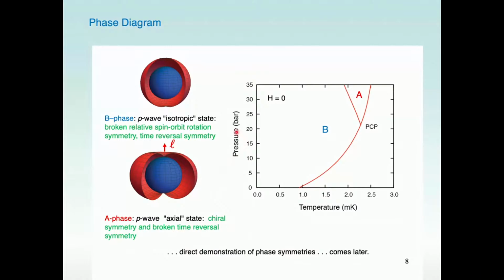Now for the B phase, interestingly, it's an unusual relative broken symmetry. It's the broken relative spin orbit rotation symmetry. And of course, it's time reversal symmetric. And the pictures are those of the energy gap around the Fermi sphere. I want to emphasize that this broken relative spin orbit rotation symmetry, which is really the characteristic symmetry of the B phase, or broken symmetry of the B phase, has nothing to do with the dipole interaction. The dipole interaction on this scale is negligible.